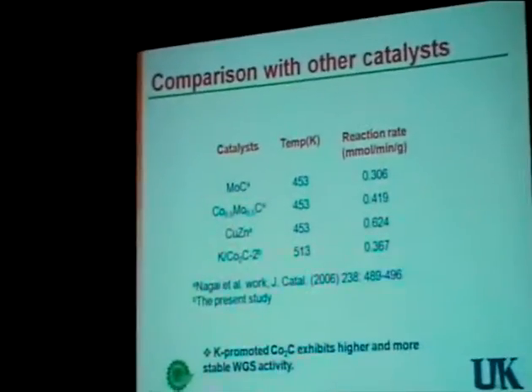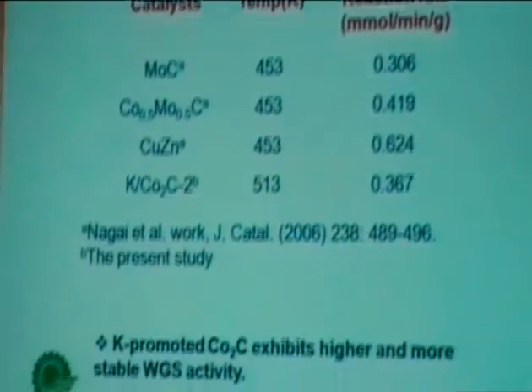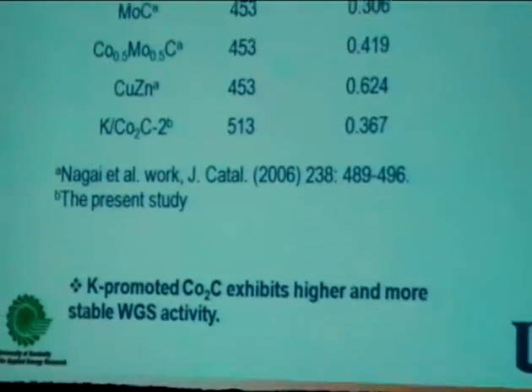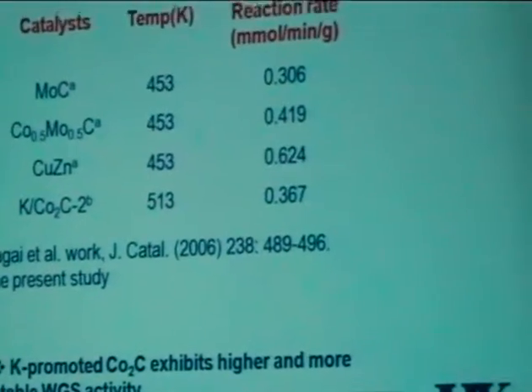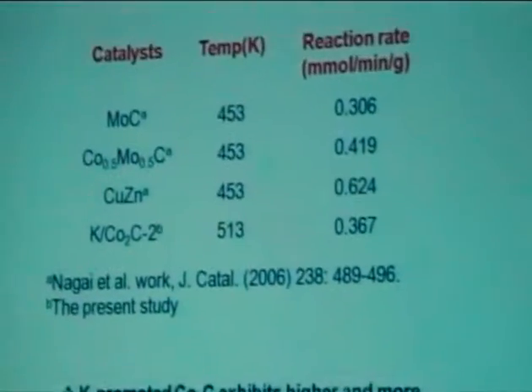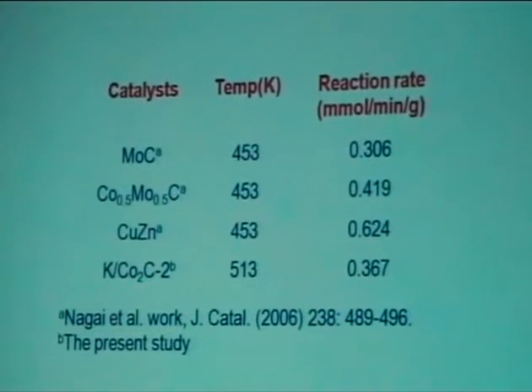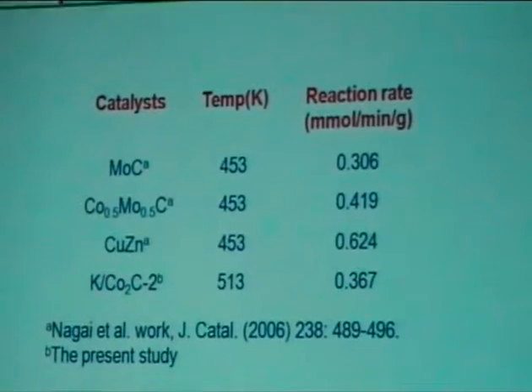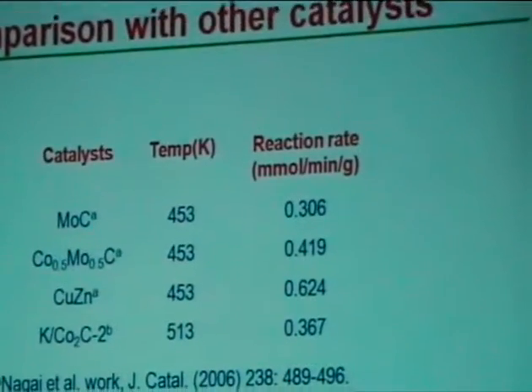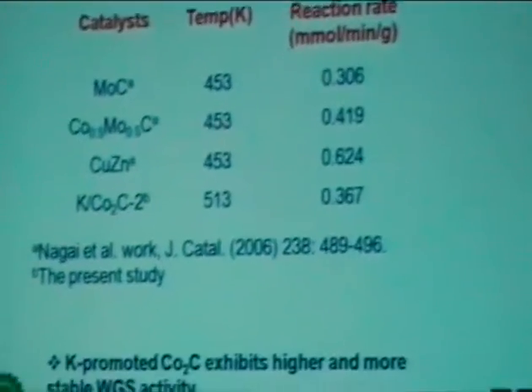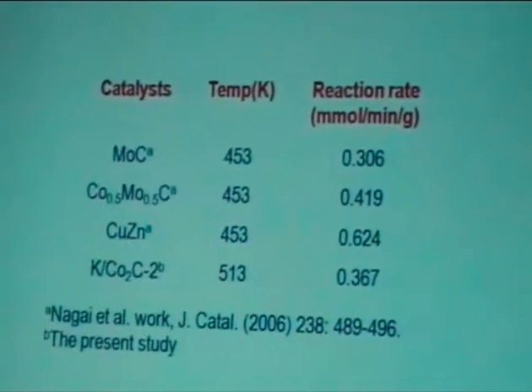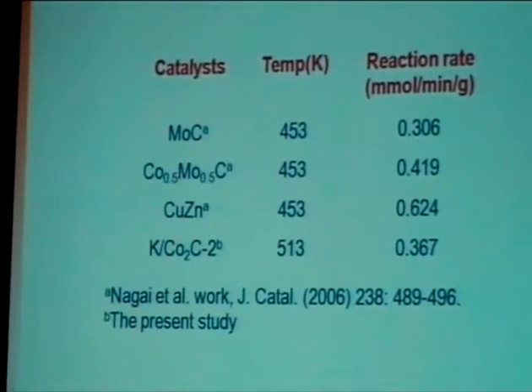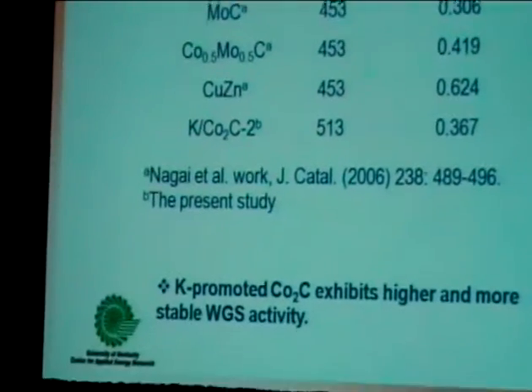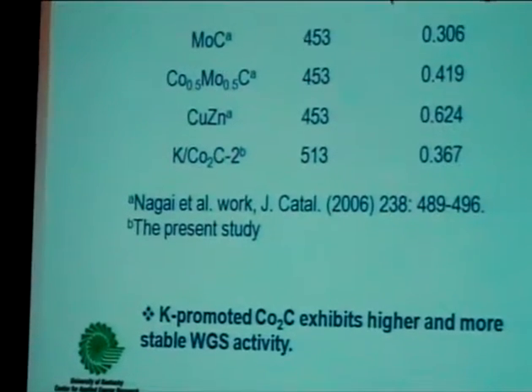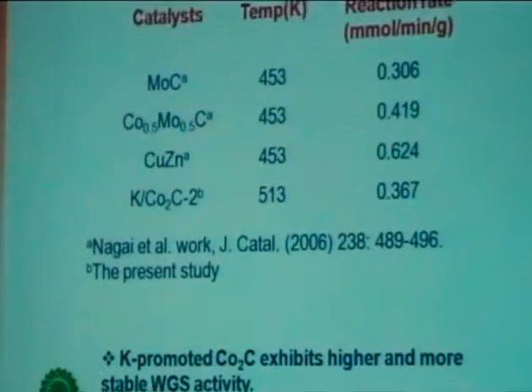And we are comparing this activity of the potassium promoted catalyst with the other paper we published. So based on the molybdenum carbide catalyst, for example, in the case of molybdenum carbide, the reaction rate is 0.306 and it is comparable with our present work, the potassium promoted cobalt carbide catalyst. Whereas if you compare this activity with the standard commercial catalyst, it is almost half of that activity. So the potassium promoted cobalt carbide catalyst is still not as good as a commercial catalyst, but it is showing some promising activity for a longer period of time.